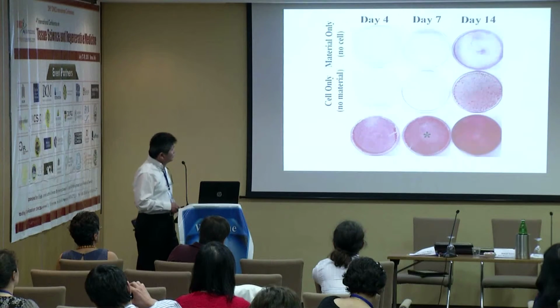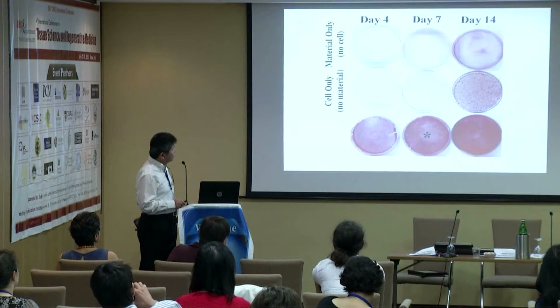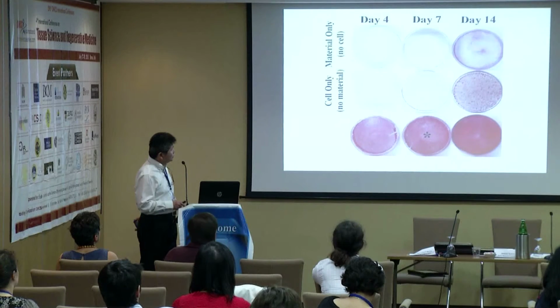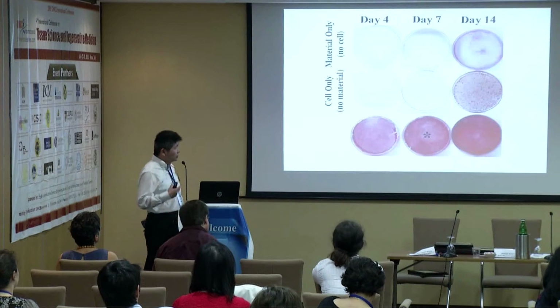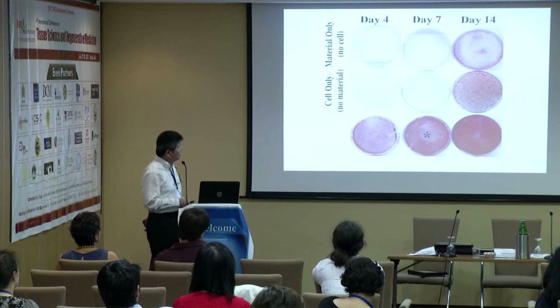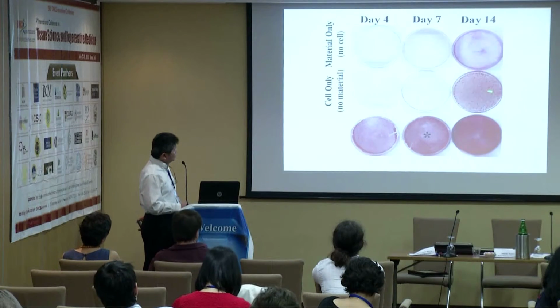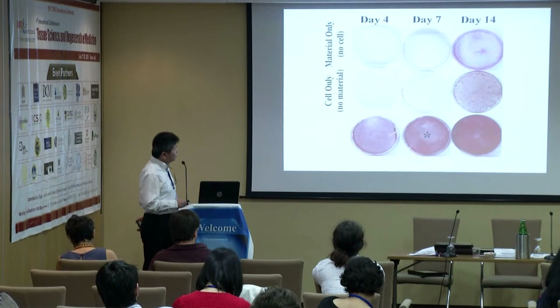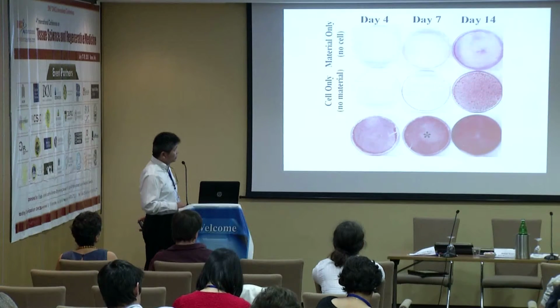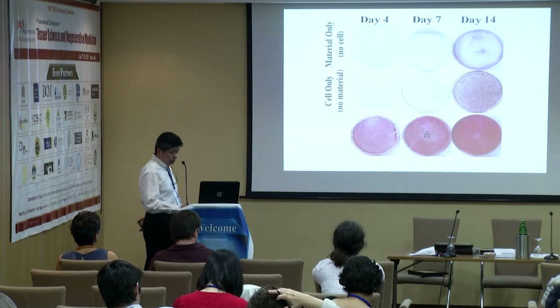And also for differentiation, in here there's only material, there's no cell, so you can see some material effect on the staining as well. This is the Alizarin Red stain for the mineral nodule. But in the second row, which is cell only, using the normal petri dish, you can see normal mineralization nodule. If we coat it with our material, you can see the mineral nodules start to form very early, and also cover the entire dishes.